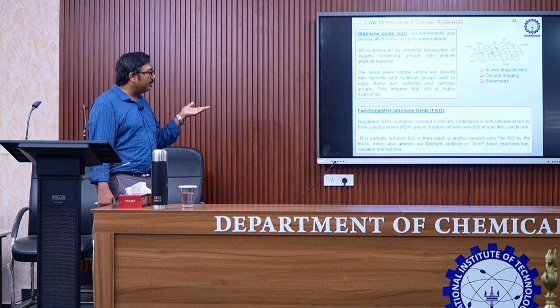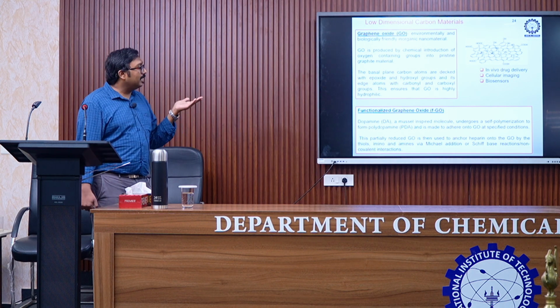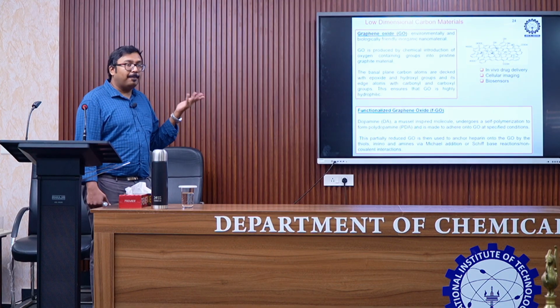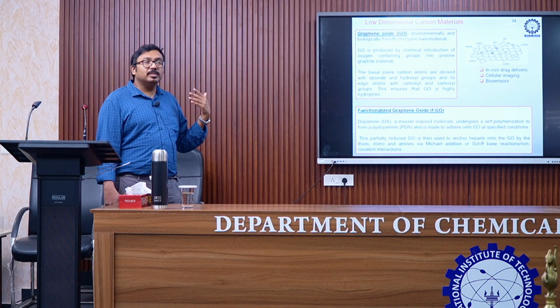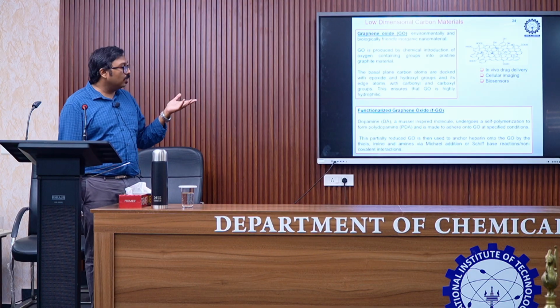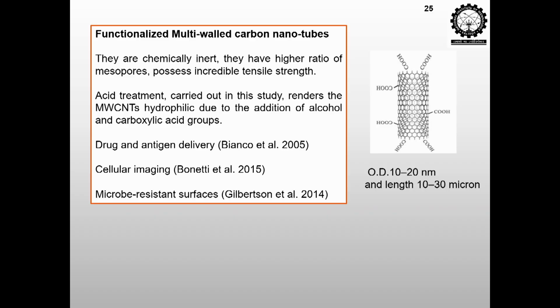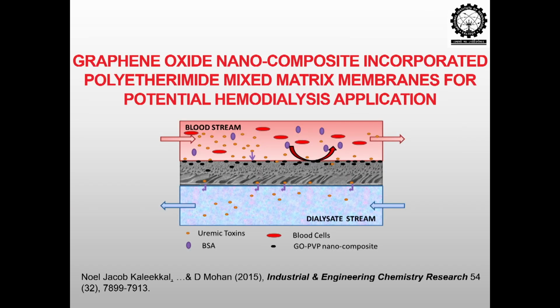functionalized graphene oxide, where we have coated the graphene oxide with heparin. The heparin was anchored to the graphene oxide using a bioglue or a bioadhesive, that is the dopamine, and carbon nanotubes. Carbon nanotubes have also been used for other applications, so we thought that they would be a good fit for hemodialysis membrane. So this is one of the works on graphene oxide nanocomposite incorporated polyetherimide mixed matrix membranes for hemodialysis application.